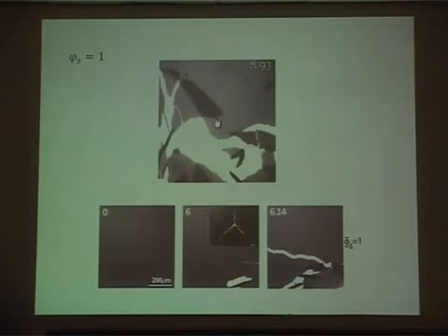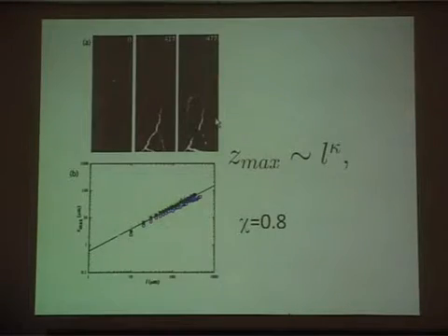And you can look at it, these are 4 micron polystyrene silica particles. They sediment very fast. So the Peclet number is such that you don't get any kind of ordering of the system. This is a very disordered structure. This is amorphous structure to start with. But you still get, because of local symmetries, probably you still get a Y-shaped thing. If you are interested, you can go up and do a crack analysis of it, and you can find out what is its fluctuations of Z max from its mean value with respect to the window size, and it gives you a critical exponent of 0.8.